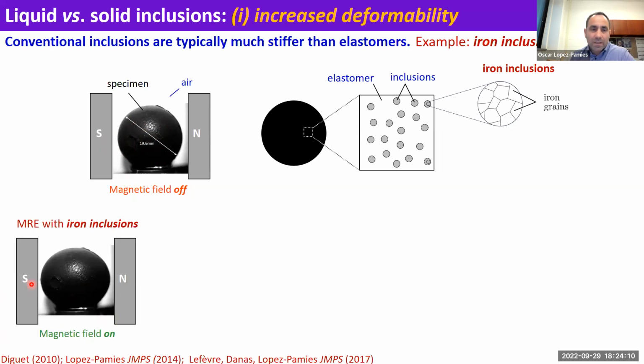What they saw is not much. This is an experiment where the magnetic field is very significant. It's more than 1 Tesla, which is a lot. And the deformation is very tiny. The reason is that iron inclusions are stiffer than the surrounding matrix. By having them there, you do two things. You make the material sensitive to magnetic fields, but you also make it stiffer, because the iron doesn't want to deform.